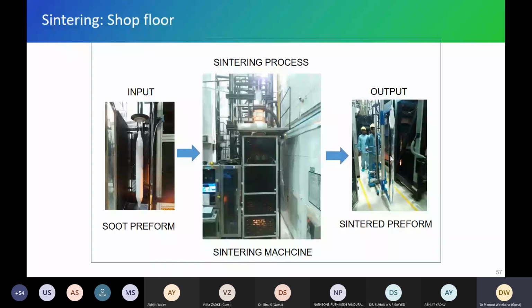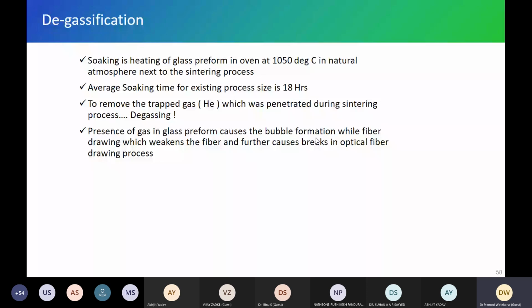So we have to be very careful that the pores are not there, so that the bubbles can be avoided. To do that, we send helium. Helium has a beautiful property that if it sits in the pores, and when it is heated, it diffuses out quickly, and we get a very clear preform that way. And now we are giving gases there, so we need to take out all those gases. Suppose there are some trapped gases. To get them out, we need to give it sufficient time.